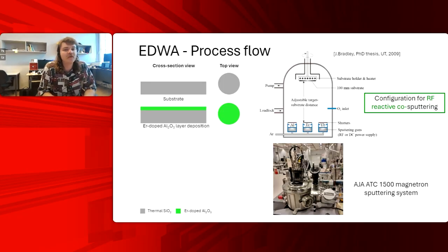So I'll bring you guys through a little bit of an erbium-doped waveguide amplifier process flow. We'll start with a substrate being silicon and thermally grown silicon oxide, where we then do an in situ deposition. You can see in that middle image here, which is actually from John Bradley's thesis, 3 different solid purity targets. This one is an example of co-sputtering with erbium, ytterbium, and an aluminum target. Once we allow that argon and oxygen gas flow to combine in the chamber, we can start to atomically sputter onto any substrate upside down on the top of the chamber there. And as it rotates, we'll start to deposit erbium-doped aluminum oxide in situ, where both of these in a single deposition step can create a doped thin film for a waveguide technology.